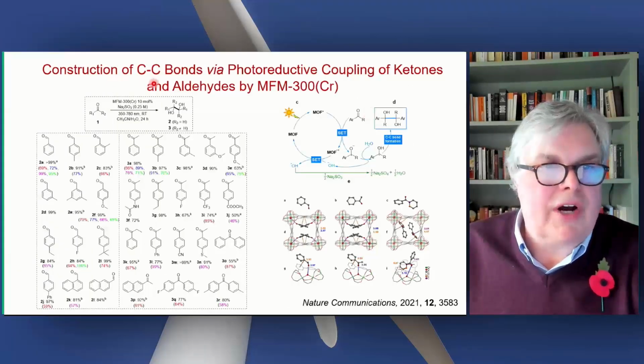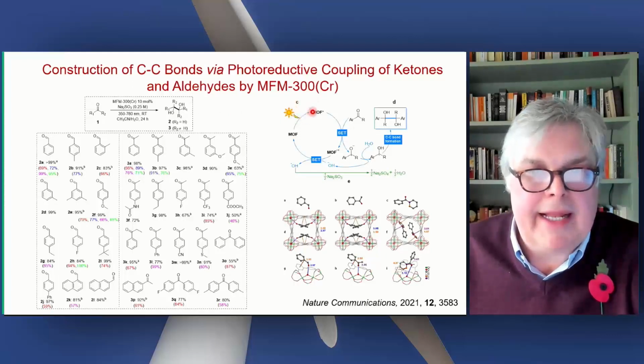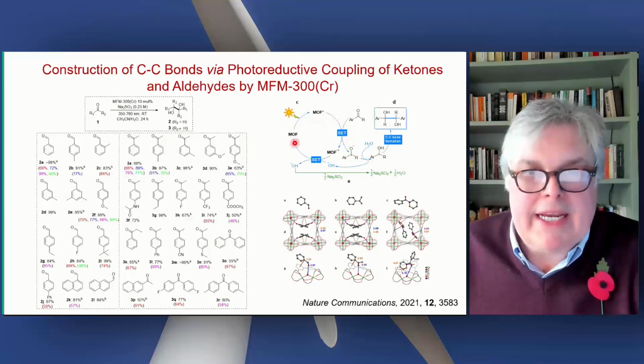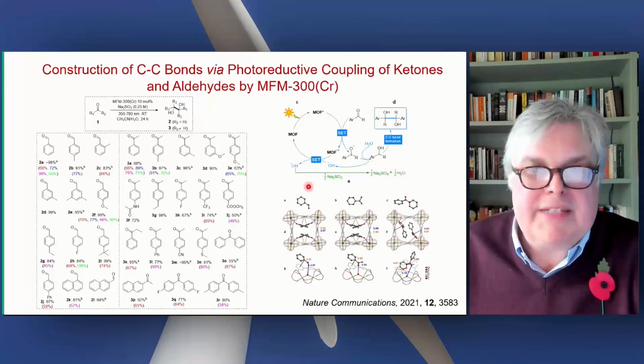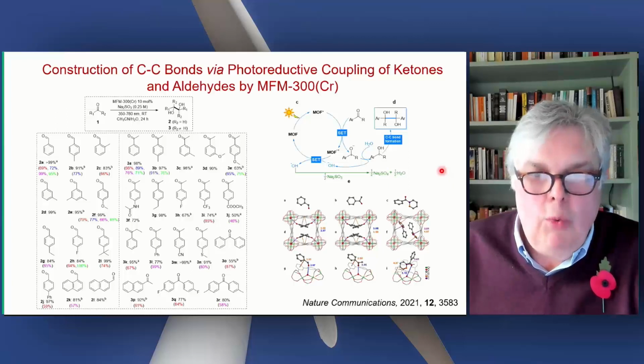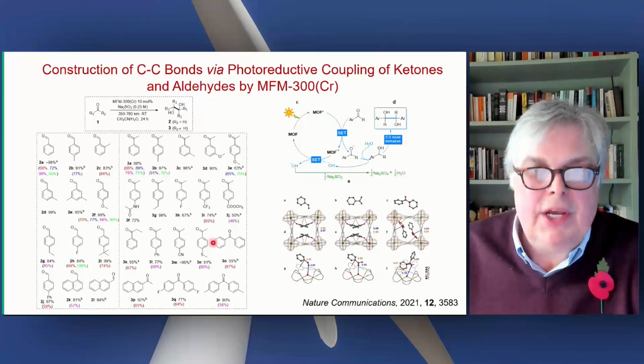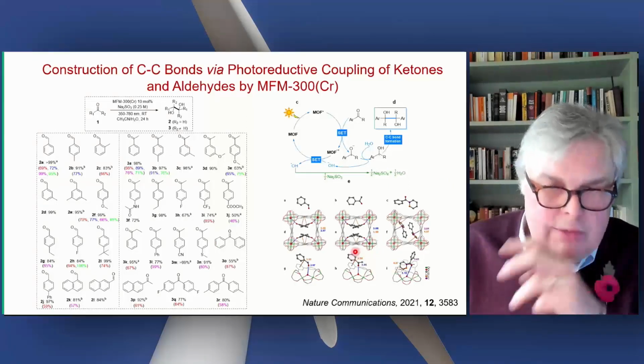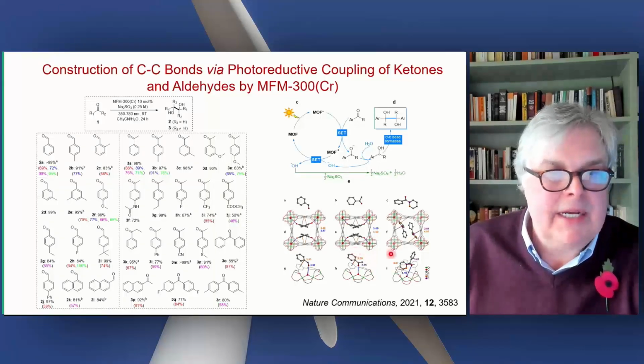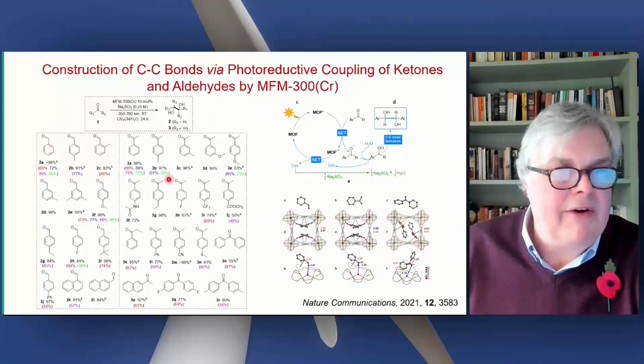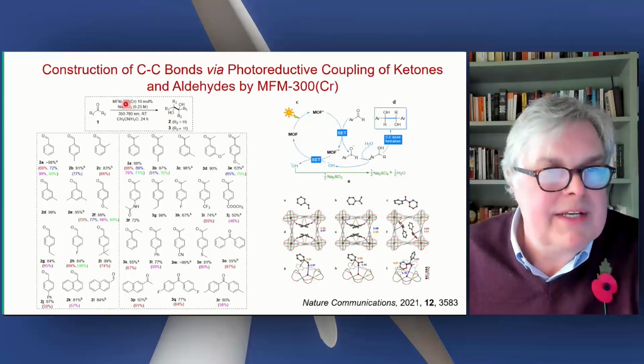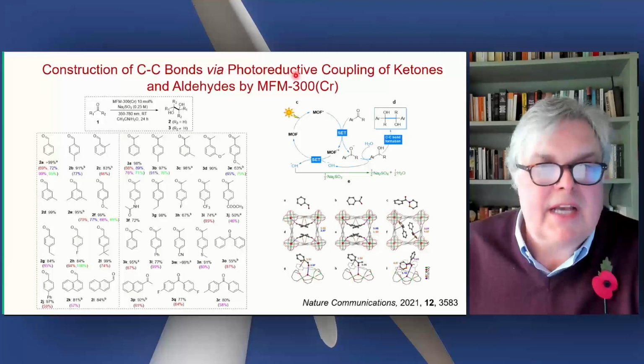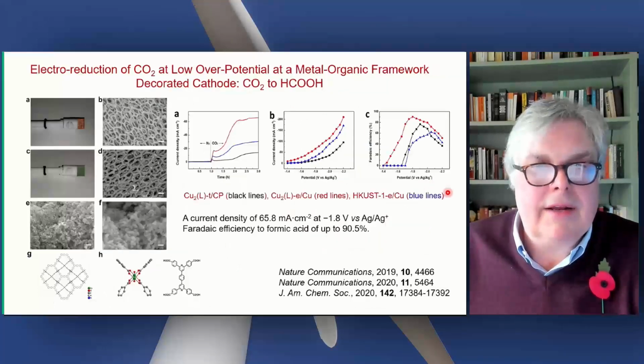We can also construct carbon-carbon bonds photochemically. So you can photochemically activate the MOF. This activates your substrates. We can trap this and follow this by EPR spectroscopy. We can do the structural analysis of where the substrate is interacting with the MOF, how it is being activated, and we have various yields of various organic materials using this heterogeneous catalyst under these conditions. I emphasize, under photoreductive conditions.